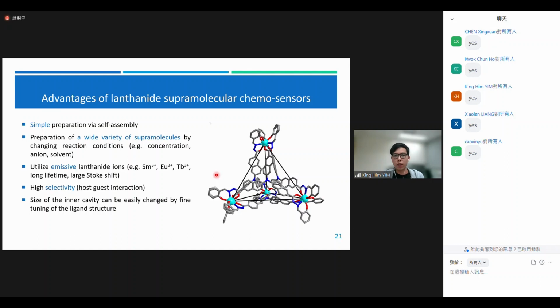Okay, and although the formation of lanthanide supramolecular complexes is very challenging, there are still some advantages of using this kind of method to make chemosensors. For example, as I said before, the preparation is very simple. You just need to mix the ligand and then the ion and reflux it, and then you can get the most thermodynamically stable product. And most of the time, the ligand consists of about 3 to 4 organic synthesis steps, which is quite convenient.